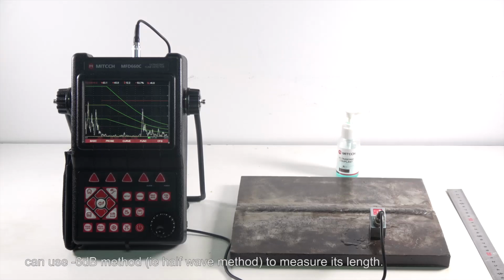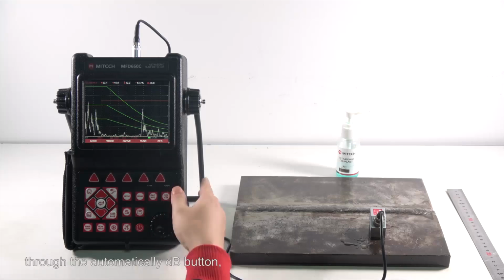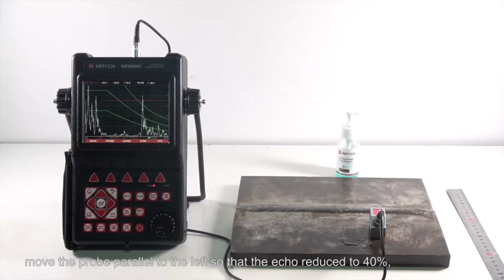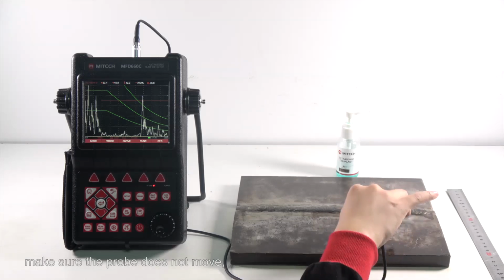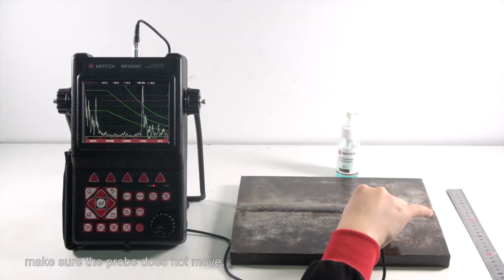According to the standard, when the defect reflection wave has only one high point and is located in area two or higher, the minus 6 dB method can be used to measure length. At this point, we increase the echo height to 80% through the automatic dB button, then move the probe parallel to the left so that the echo reduces to 40%. Make sure the probe doesn't move.